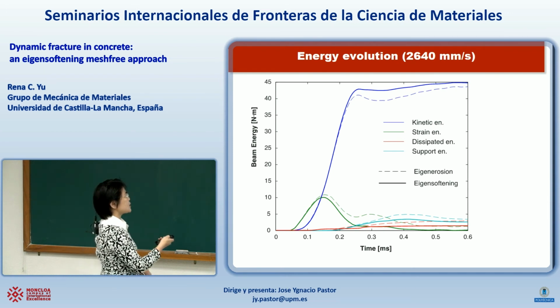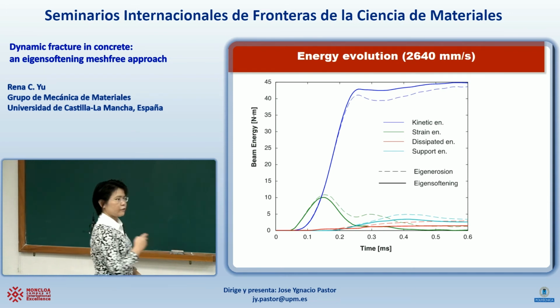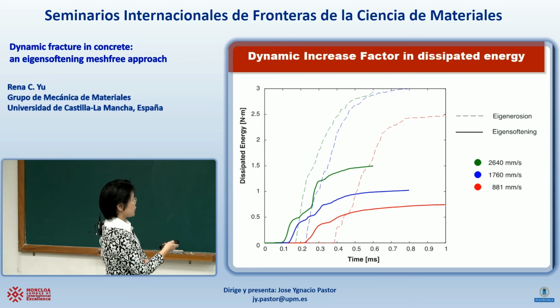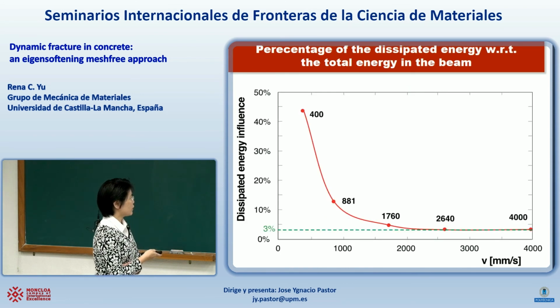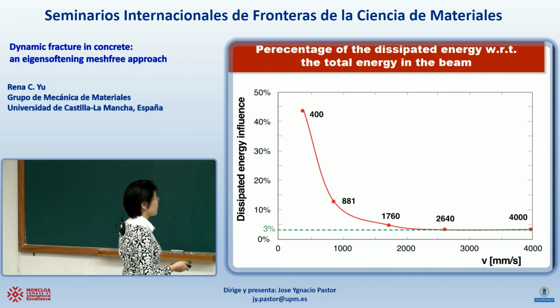In any case, what we see is that the kinetic energy is the significant part. And if we plot, because these three correspond to eigenerosion and this corresponds to eigensoftening, again the static value is like 0.7 joules. So the dynamic increase factor is between 1 and 2 for these three velocities.